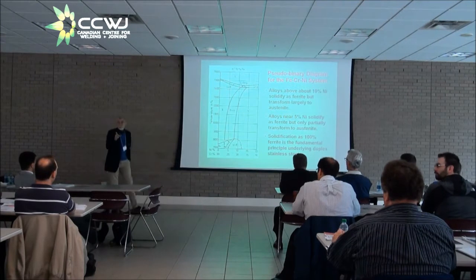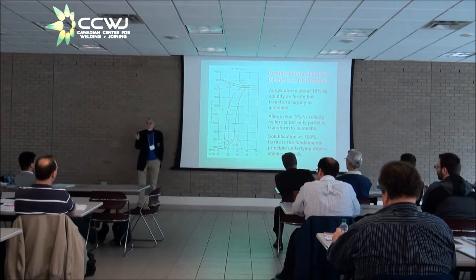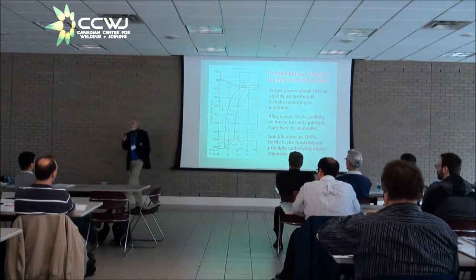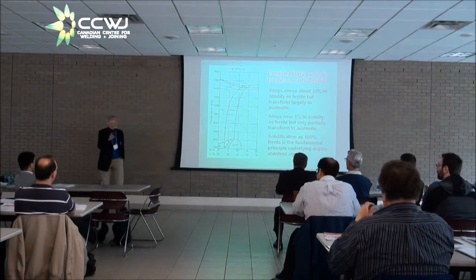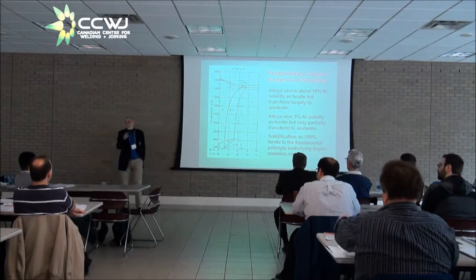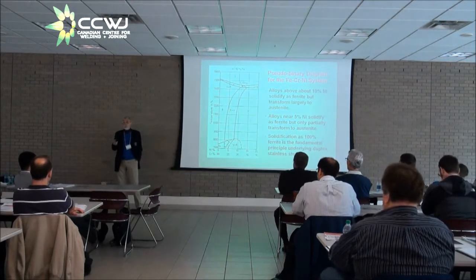However, if you take that 304 base metal and you melt it with a gas tungsten arc torch, no filler, just melt, and then measure the ferrite, you will find there's some ferrite. That's because during solidification you get some formation of ferrite, and some of that ferrite survives to room temperature. To get rid of it, you need to cause chromium to diffuse out of the ferrite and nickel to diffuse into the ferrite. Ferrite and the austenite have different chemical compositions.